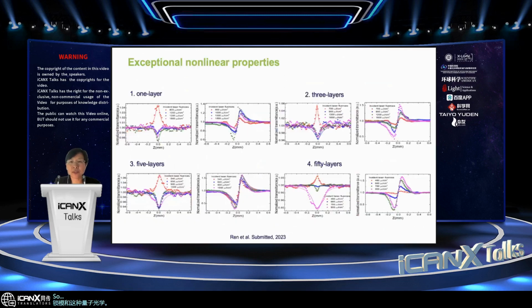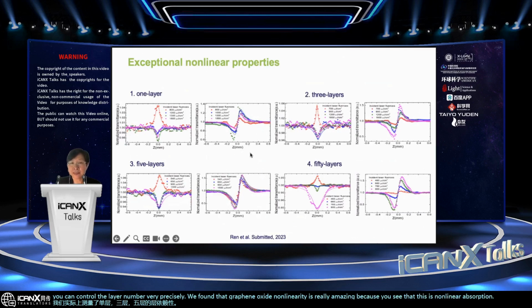In our case, we also quantified the nonlinear property of the graphene oxide layer. We want to know what the nonlinearity is for a monolayer, whether there is any nonlinearity. We measured the layer dependence for single layer, 3-layer, 5-layer. Actually, you can control the layer number very precisely. We found that graphene oxide nonlinearity is really amazing, because you see that this is nonlinear absorption, and this is nonlinear refractive index.